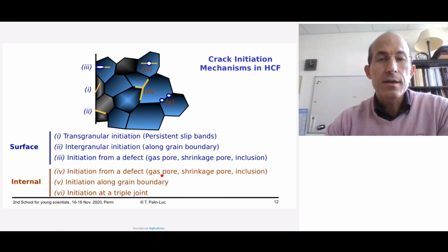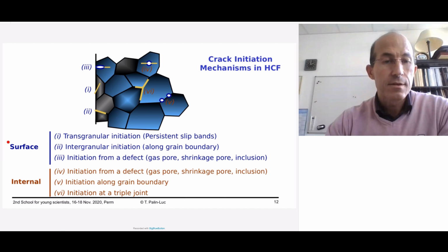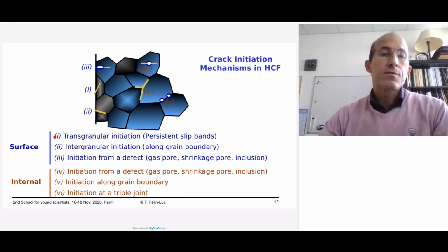If I want to summarize the crack initiation mechanisms in high cycle fatigue, mainly the crack initiates at the surface. So this is the most common case of crack initiation from low cycle fatigue to high cycle fatigue, whatever the number of cycles. The difference between low cycle fatigue and high cycle fatigue is that in high cycle fatigue, the crack initiation is very localized. We will come back to that in a few minutes. So the initiation's causes are mainly these.